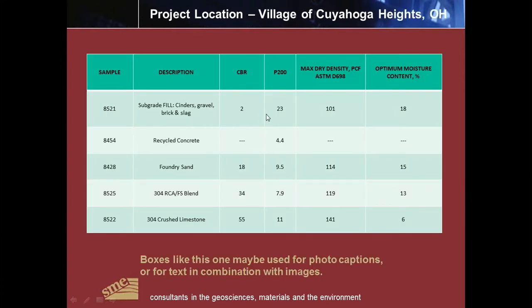We did several laboratory tests on the different materials in this project. That included the subgrade, the fill cinder material. They had a low CBR of 2, and a high percent passing the 200 sieve, 23%, which is predominantly a silty material, not clayey. It has a relatively light density of 101 pounds per cubic foot and an optimum moisture content of 18%.